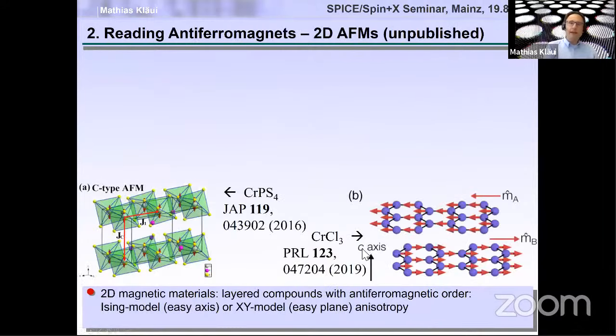Then just a few words on layered antiferromagnets. This is something which we recently started to work on, which I think is very exciting. There's lots of literature out there. For instance, these trihalides, such as chromium chloride, are very exciting materials because they are layered antiferromagnets, which for one layer is a pure ferromagnet. For two layers, it's a pure antiferromagnet because you are fully compensated. And then for three layers, again you have one layer which is an uncompensated moment. So you can switch between ferromagnet and antiferromagnet by changing the number of layers.